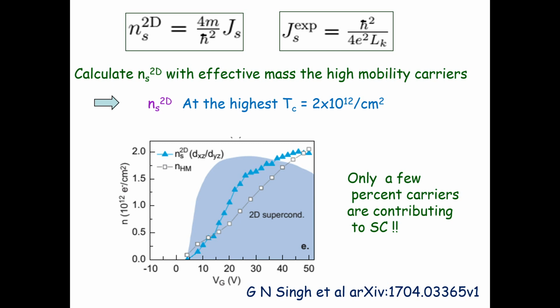So this is the data, whatever I am plotting here. This is the number density of high mobility carriers that I got from the two-band analysis. It follows this path, and the number density of carriers that I am getting from this analysis is somewhere here. They are reasonably close to each other. But what I am saying is, if I compare them with the total number of carriers, they are only 2 to 3%. This is the current picture for superconductivity.